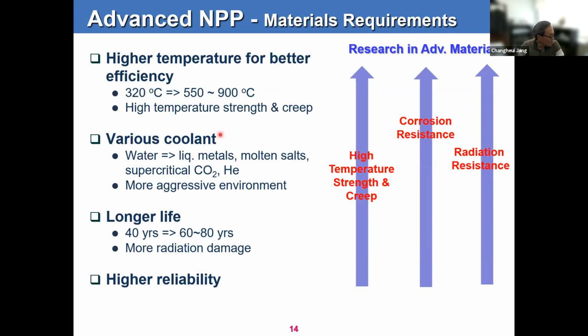And also the coolants. Right now it's mostly water, but we have a variety of liquid metals like liquid sodium, liquid lead, or lead bismuth eutectic. And also you have the molten salt, a fluoride-based salt and chloride-based salt, and the supercritical CO2 and the helium. And because of those various coolants operating at those temperatures, we are expecting that it will be a significantly aggressive environment for the material. So you have to worry about the corrosion, and you have to figure out how to mitigate that corrosion or how to develop a better material with better corrosion resistance.